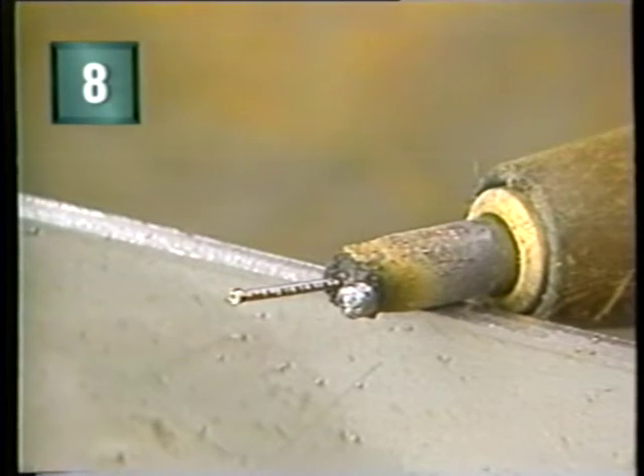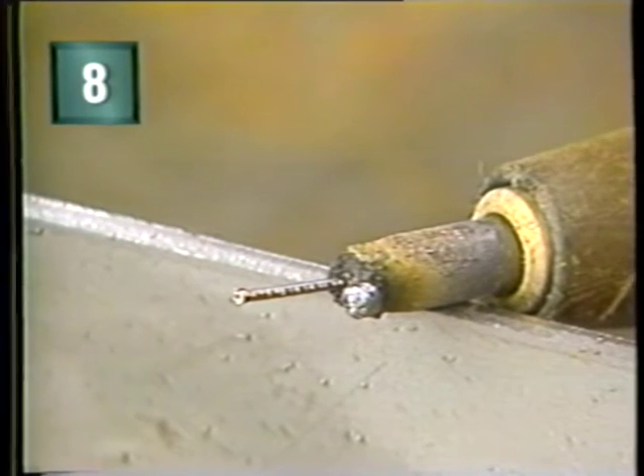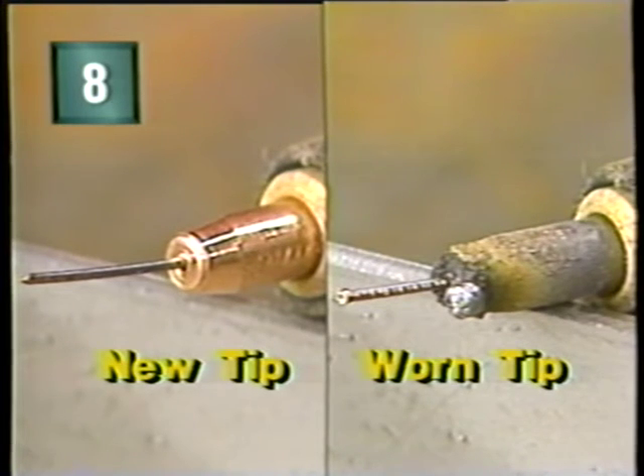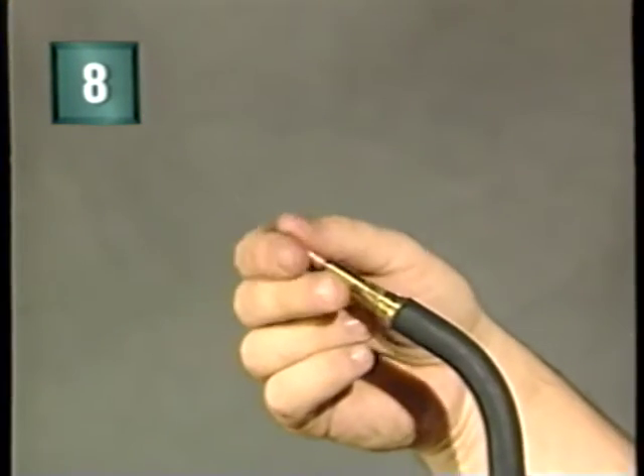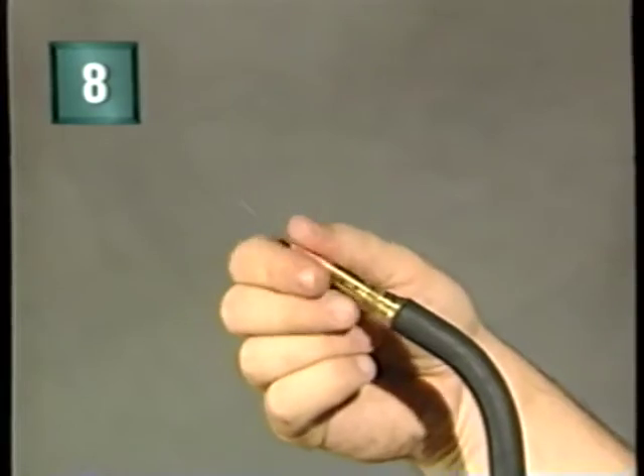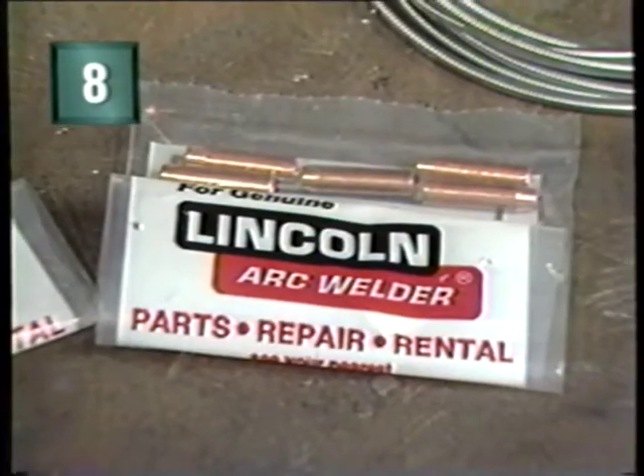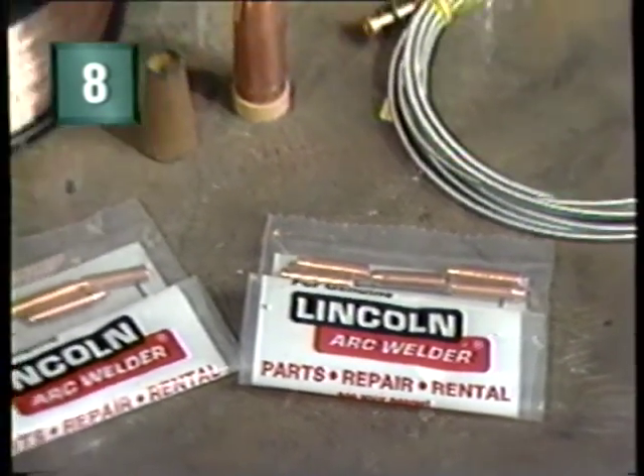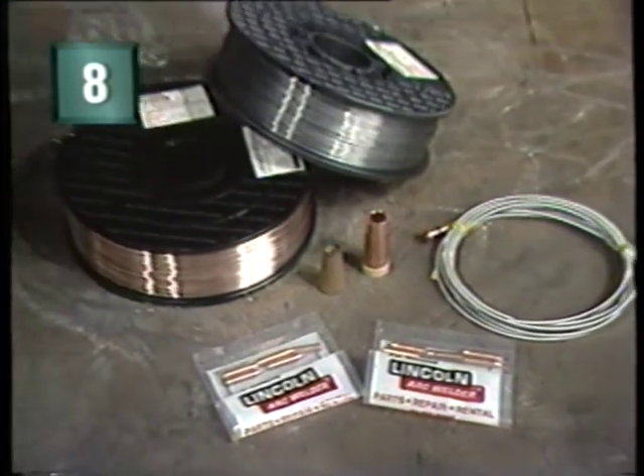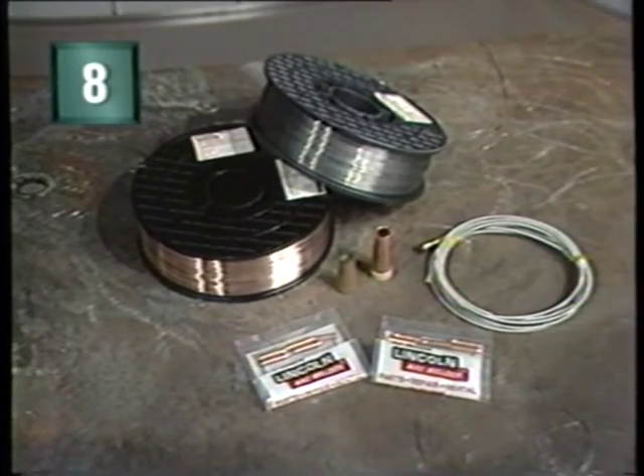Keep in mind that the contact tip does wear out and occasionally needs replacing, typically when the hole in the contact tip becomes elongated or if the tip contacts the molten puddle. Because of the gun assembly design, the changeover is quick and easy. Replacement tips, wire, and other welding supplies are available at your local welding supply distributor. The Welder's Guide has a complete list of part numbers. And of course, should your welder require professional service, your Lincoln Field Service Shop is only a phone call away.